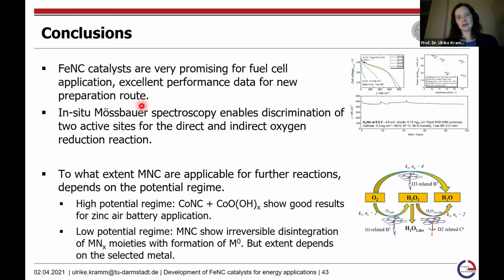From in situ Mössbauer spectroscopy, we were able to discriminate two active sites, one for the direct reduction and one for the further reduction of hydrogen peroxide to water. These Me-N-C catalyst materials might also be interesting materials, for instance, for metal-air battery applications in combination with some oxyhydroxide systems. When you go for the low potential regime, so far, at least if you go quite negative, you see an irreversible disintegration, but we need to investigate this further in order to see until which range they basically remain stable.